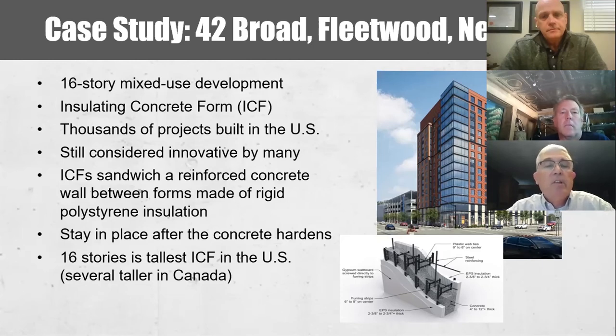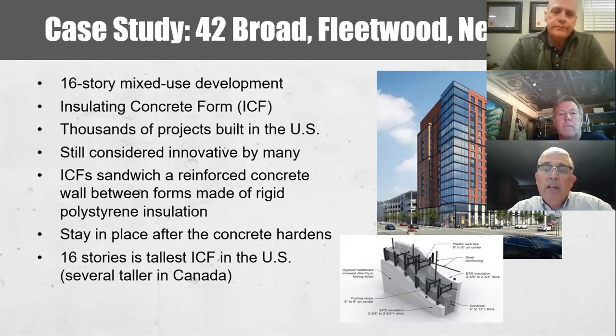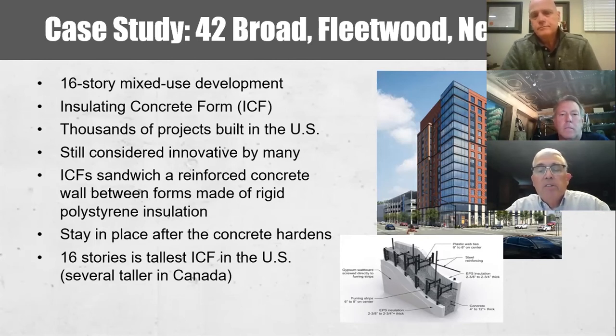This project used insulating concrete forms, and you see a cutaway illustration at the lower portion of the slide. Insulating concrete forms, it's a stay-in-place concrete forming system. It features typically two face shells of insulating materials, so two layers of foam in this case, and those layers are held apart by those black elements running transversely across the formwork. That holds those face shells the required distance apart to create a cavity for ready mix concrete and reinforcement.